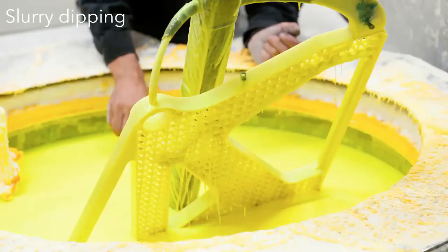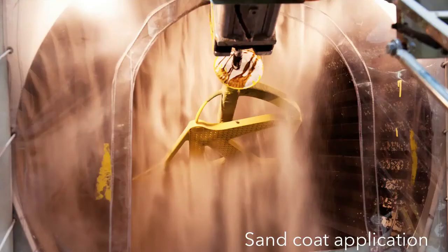This is the slurry dipping process. It's a color indicating liquid ceramic slurry. So it goes from this green-yellow to an orange, so that you can maximize process efficiency, and don't have dry parts sitting. You generally repeat this dip and then sand coat application anywhere from 4 to 12 times to build up a layer between 4 and 20 millimeters thick. You're building up the mold in this process.